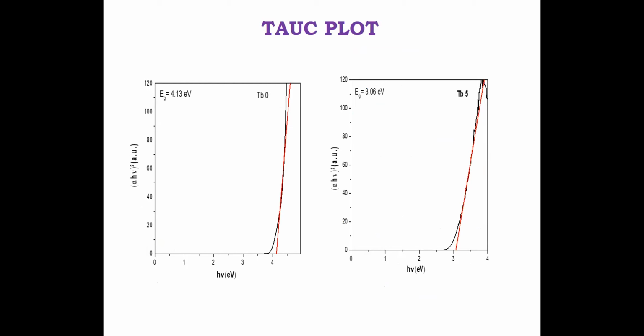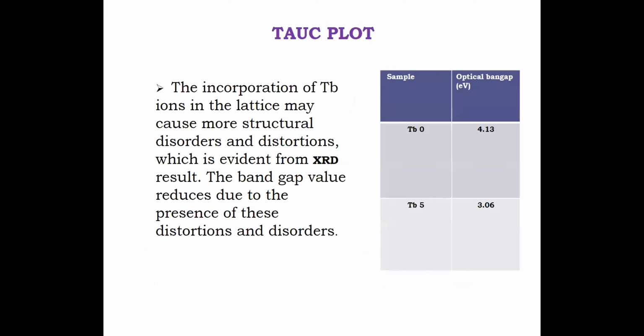The optical band gap values of the samples are calculated using Tauc plot. The calculated band gap values are given in the table. For TB0, it is 4.13 electron volt, and for terbium-5, it is 3.06 electron volt. So the incorporation of terbium ions in the lattice may cause more structural disorder and distortion, which is evident from the XRD result too. And due to the presence of these distortions and disorders, the band gap value reduces.